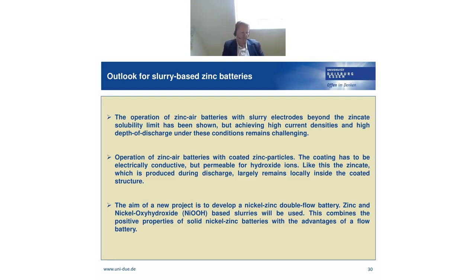Generally, zinc air batteries, of course, have a small disadvantage that they have a large voltage gap between oxygen evolution and oxygen reduction. So this will always lower the voltage efficiency, so the overall efficiency is maybe 40, 45 or 50%. So one possibility is, of course, to get rid of the oxygen electrode and replace it with a different chemistry. So we have a new project which has just started, and the aim is to develop a nickel-zinc double flow battery. So we will have slurries flowing on both sides, on the anode side and on the cathode side.